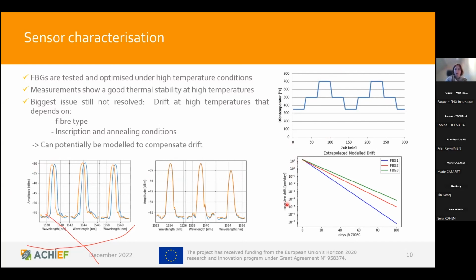However, this negative drift you see here decreases a lot over time and can be taken into account numerically. So again, we prove the necessity for drift compensation with the sensors, but that is a well-known issue and can be taken into account in the experiments. To give you an idea, 10 picometers per day roughly result in 1 degree Celsius. So this drift in the beginning is in a relevant range, but diminishes over time to be basically negligible.